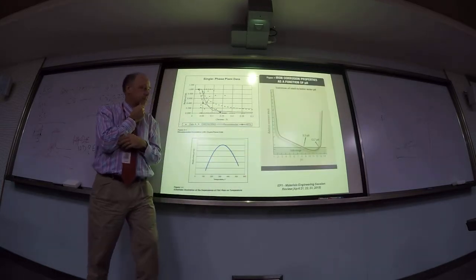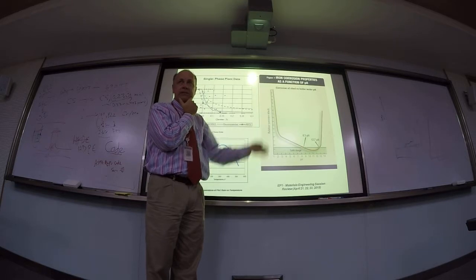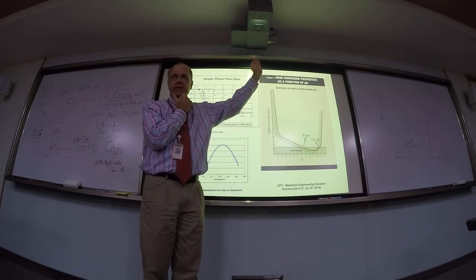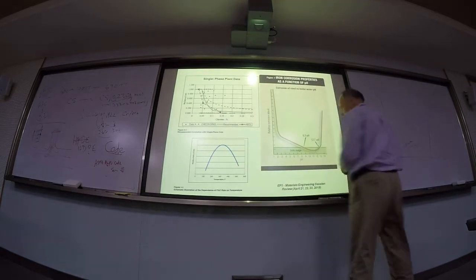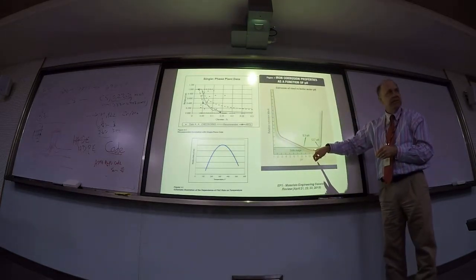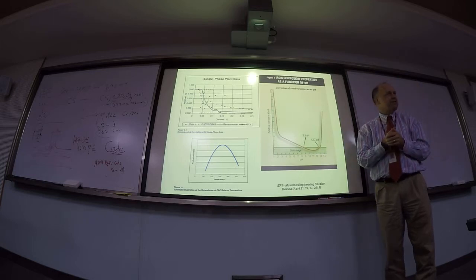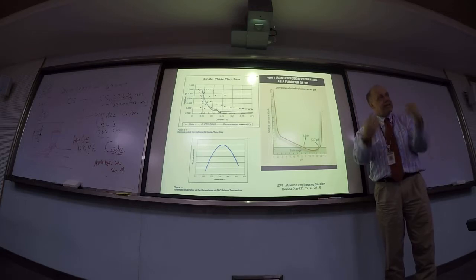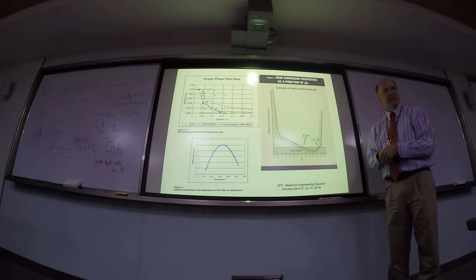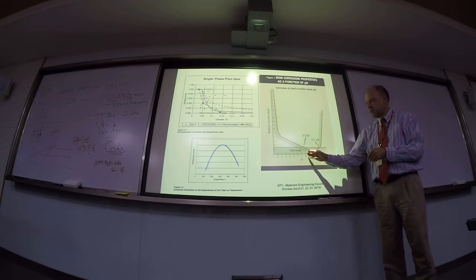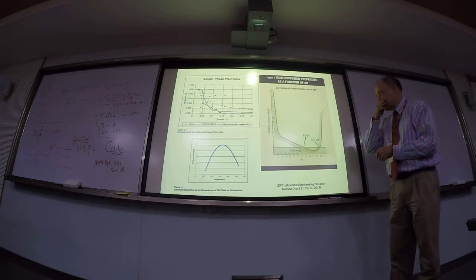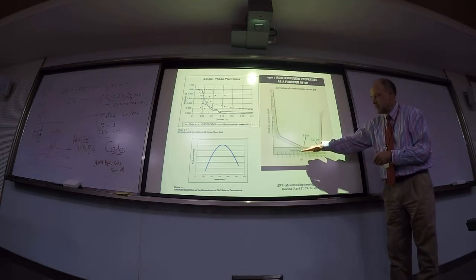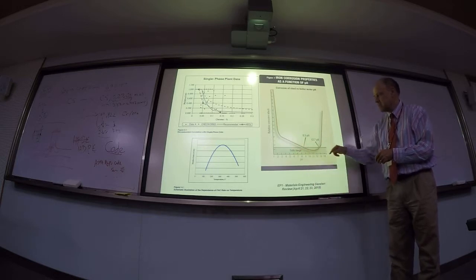And what does this one show? FAC rate again. FAC rate versus pH, right? Looks like the minimum pH is 11.5. So why don't we just pick 11.5 pH? It's very hard to get 11.5. We need to add a lot of additives to the condensate to get that, just too much. We used to control at 9.2 and they moved it up to 9.4, but that's kind of a practical limit. Okay? But anyhow, we're in a good range down here with the pH. So know that shape of that curve.